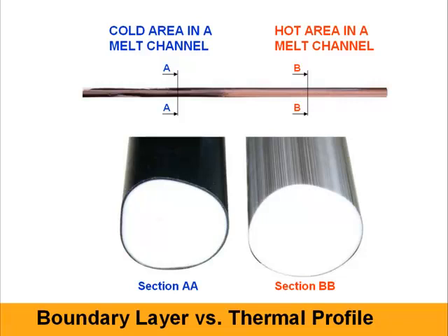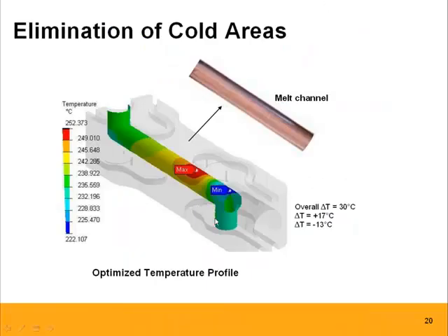An optimized manifold for color change is actually a hot runner that has a uniform temperature profile. Hotter is actually not bad, but the best situation, of course, is a uniform temperature profile where we then can, as operators, play with the temperatures as we need. We don't want to go too hot either, of course, because eventually we start burning the material, and that's not a desirable outcome either.